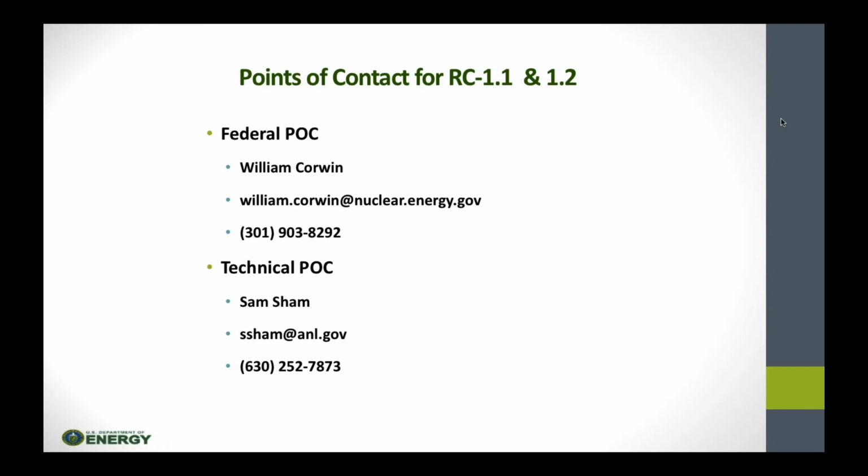For RC1.1 near-term research, by cladding, do you mean a thin coating to provide corrosion resistance? I'm glad that that question was raised. We're specifically not interested in thin coatings. Thin versus thick is probably a relative term, but we're looking for something that is more traditionally applicable to weld overlay cladding. Those typically are at least a tenth of an inch and more commonly 2 to 3 tenths of an inch thick. Thin coatings, things that may be applied such as cold spray or other types of coatings that are microns thick or fractions of millimeters thick do not fall into the area of interest for this proposal for multiple reasons.